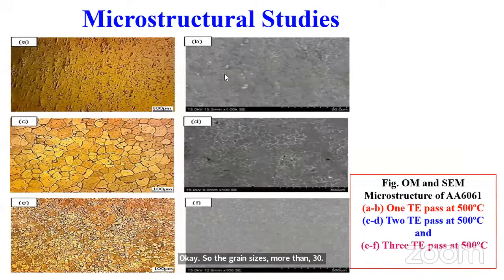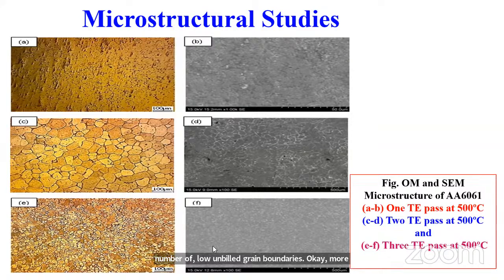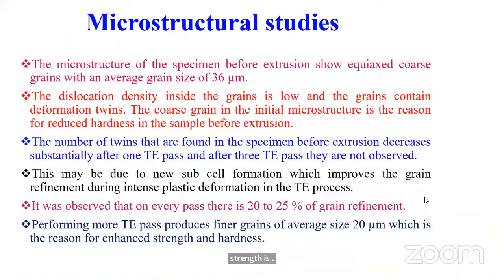After the material is processed with the twist extrusion, you can see the grain size is reduced. You can see a large number of low angle grain boundaries, more at 500 degrees centigrade, that is E to F, the material processed at 500 degrees centigrade, so the material strength is improved. At the same time, the hardness of the sample also increased.